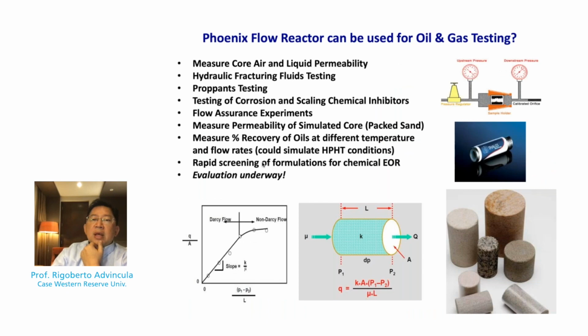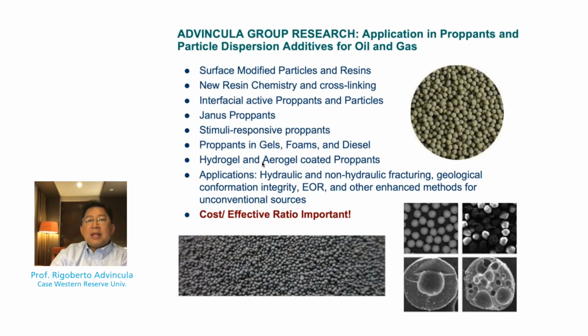We are actually able to test the permeability of fluids on these particles, measure the differential pressure or temperature under higher pressure and higher temperature conditions. So in other words, this could be a core flooding experiment that can be done in the lab.